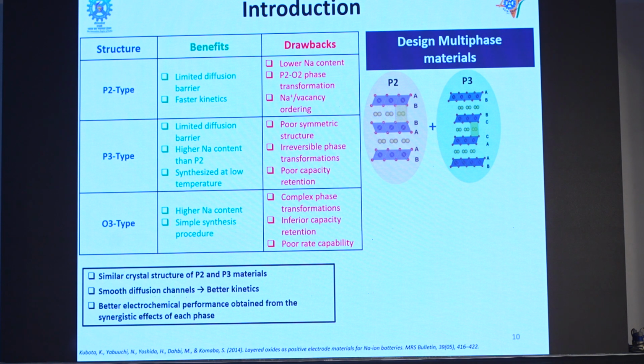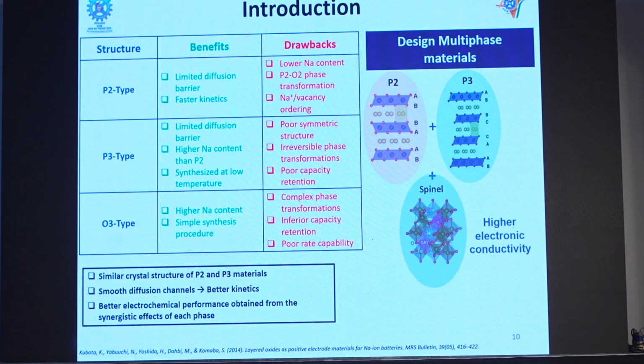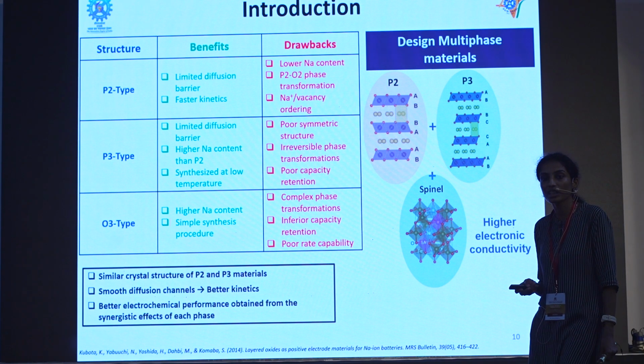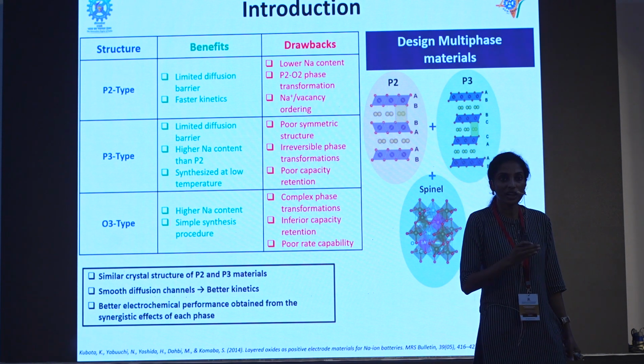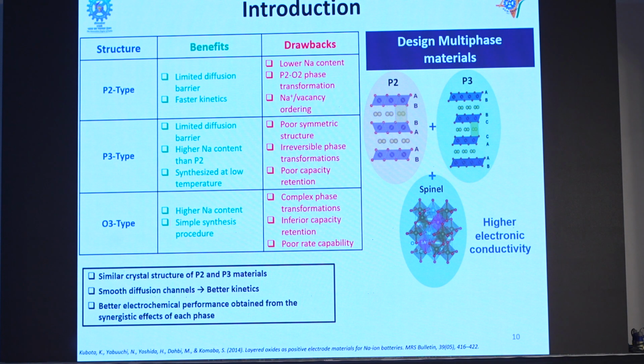We have investigated P2 and P3 separately. I'm not going to show it here. And the P2, P3 composite we have also investigated, and we figured out the P2, P3 composite is behaving better. But in this special work, we are also going to incorporate a smaller spinel component in the crystal structure. The spinel components actually are not subjected to sodium ion intercalation or extraction because they are thermodynamically not favoring sodium ion intercalation. But the advantage is that by adding a spinel domain to the P2, P3 domains, we can impart higher electronic conductivity to our overall material. That was the major idea.